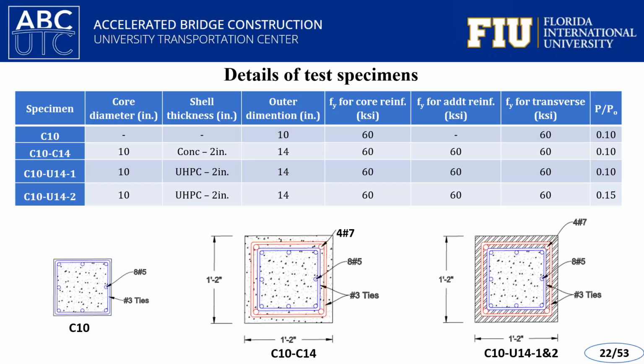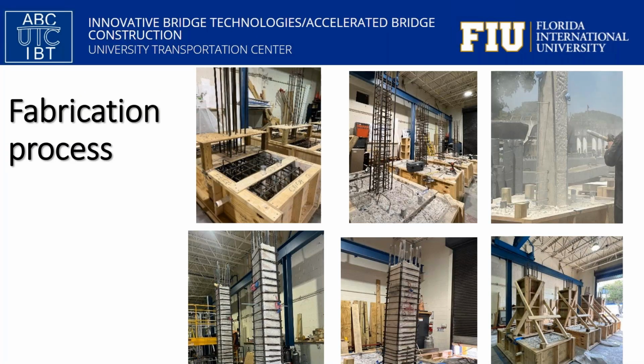One using normal strength jacket, which is C10, C14, and 2 using UHPC jacket, C10, U14, 1 and 2. For all retrofitted columns, the jacket were 2 inches thick. One of the UHPC jacket column was tested under higher axial load to assess the influence of axial force on performance. The fabrication process was completed in several steps.